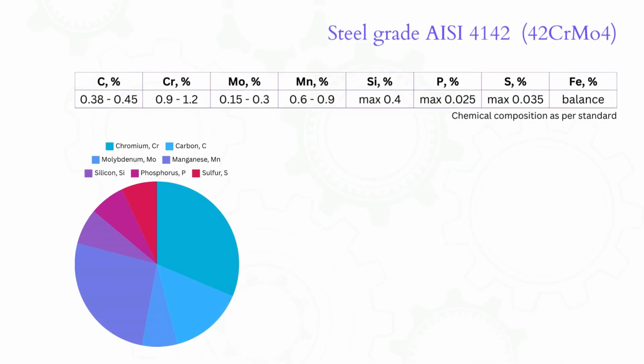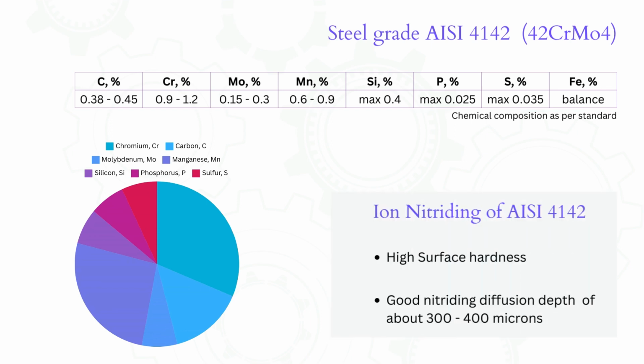This case stands out, and it is interesting because this steel grade is usually very good for nitriding and achieves a great balance of surface hardness and diffusion depth, as we will look into in another of our studies. Nevertheless, the requirement was for a small diffusion depth of less than 100 microns.